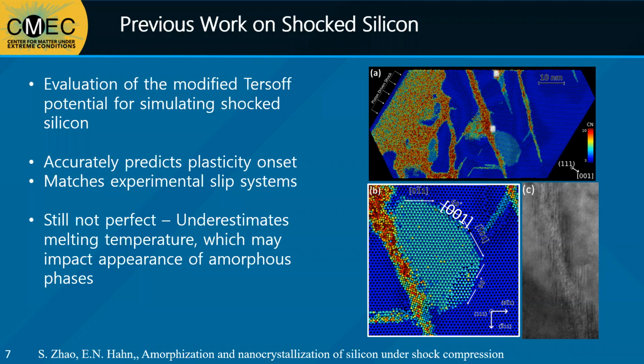Other factors for its validation include development of dislocations along predicted slip systems and the use of density functional theory to compare stacking fault energies. This potential also predicts amorphization, which is validated by Zhao's shock experiments, where amorphous zones were observed upon recovery and characterization of the silicon samples.